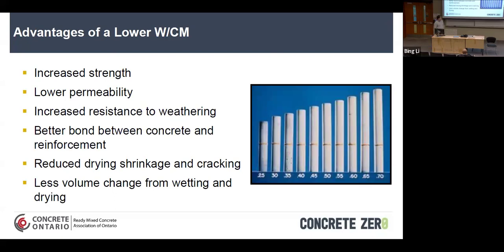So the advantage of using lower water cement ratios in concrete: you get increased strength, lower permeability, as we just talked about. Resistance to weathering, freeze thaw, yes, because of the low permeability, because of the increased strength. Better bond between the concrete and the reinforcement, usually, depends. If it's too dry, that could be a problem as well. If you have proper consolidation, that's not going to be a problem. Can it reduce drying shrinkage? Yes. It's going to increase autogenous shrinkage though. So there is a limit for drying shrinkage. It's around 0.4 water cement ratio. And then there's going to be less change in volume when you wet the concrete and dry the concrete.